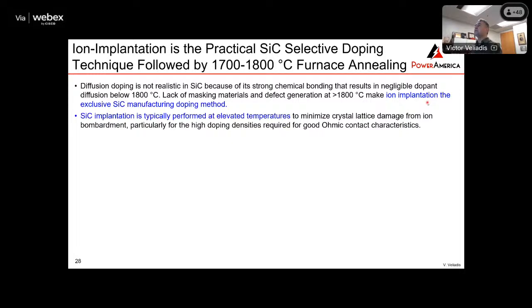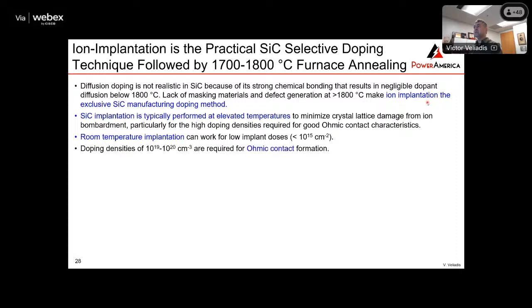You need to perform it at high temperatures in order to keep the quality of the crystal. Because of the hardness of silicon carbide, the implantation is at very high energy. So you're really bombarding the wafer, and that can be a problem. You can do room temperature implantation as long as you only require low implant doses.